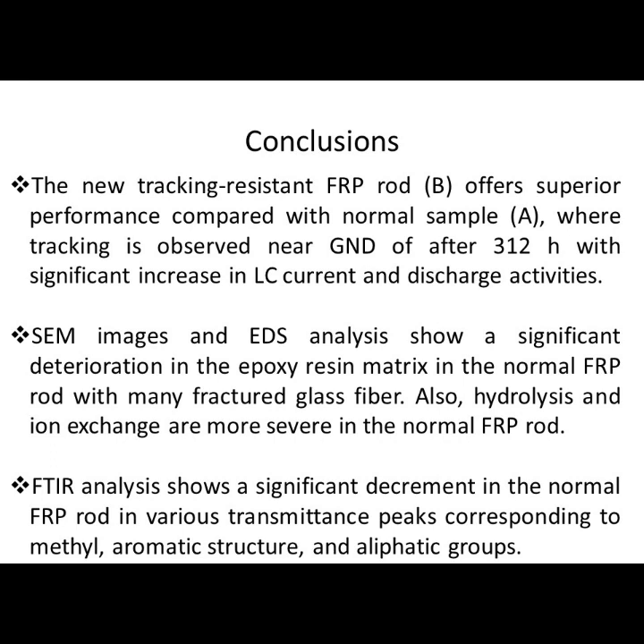This slide shows the conclusions of the work, where the new tracking resistant FRP rod shows a superior performance compared with the normal FRP rod, where tracking takes place in the normal FRP rod after about 300 hours near the ground electrode with a significant increase in the leakage current and also the discharge activities. Both SEM, scanning electron microscope, and energy dispersive X-ray spectroscopy analysis showed a significant deterioration in the epoxy resin matrix in the normal FRP rod with many fractured glass fibers, and also hydrolysis and ion exchange were more severe in the normal FRP rod. And also the FTIR analysis showed that a significant degradation in the epoxy resin matrix was detected in the normal FRP rod compared with the tracking resistant FRP rod. Thank you.